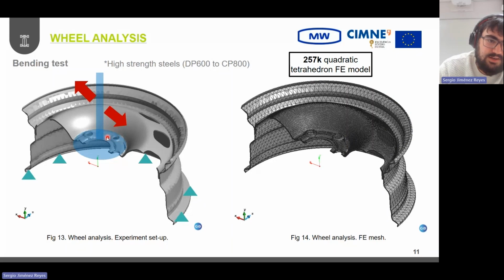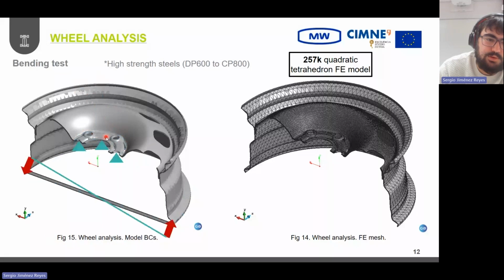And we convert these boundary conditions applied experimentally into these ones here, which are equivalent. Basically, what we are doing is restraining this region here, which is in contact with the surface. And we apply the bending through this torque force, through this bending force on this bottom layer of the wheel. And from that, then we